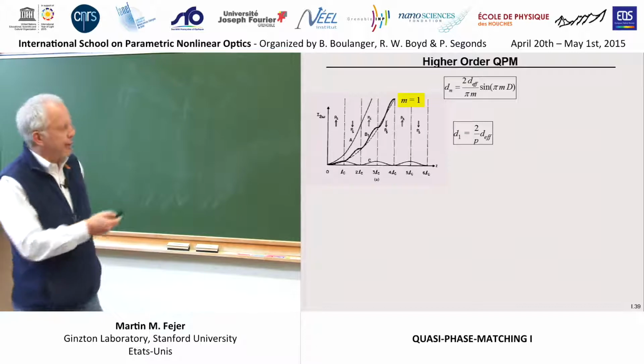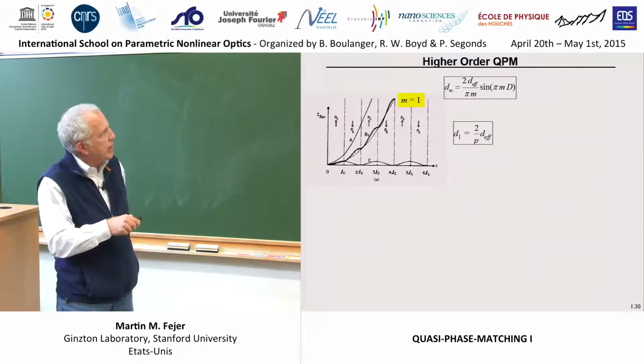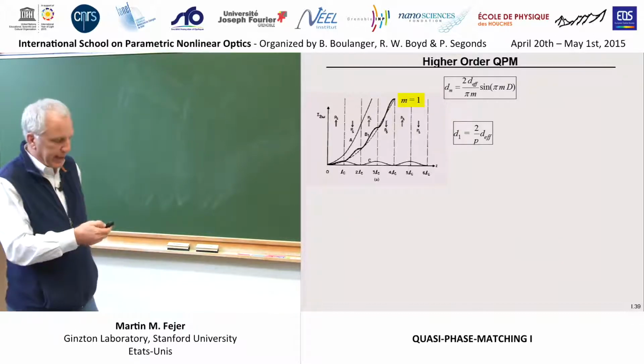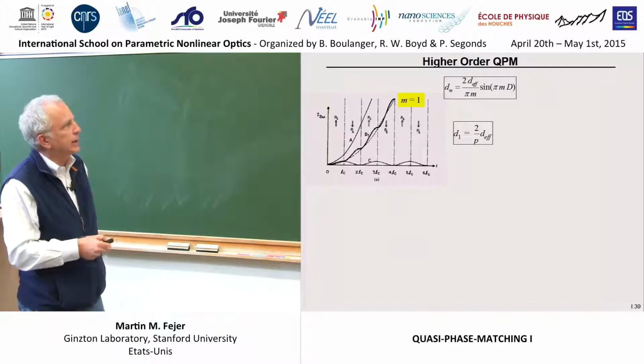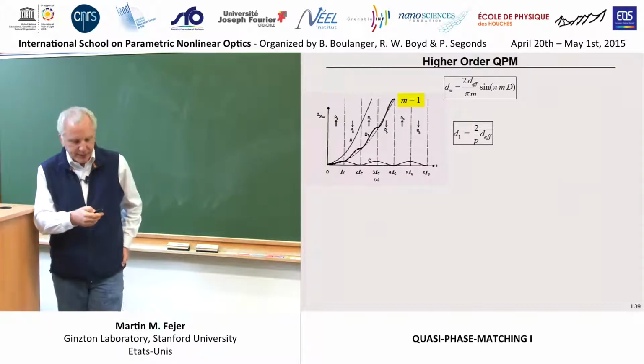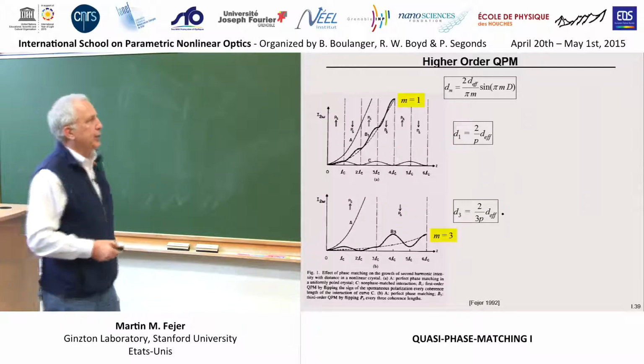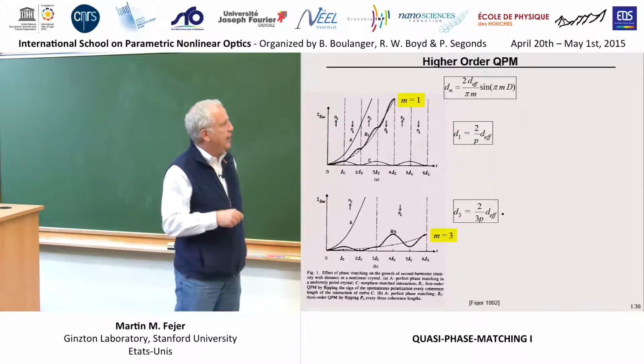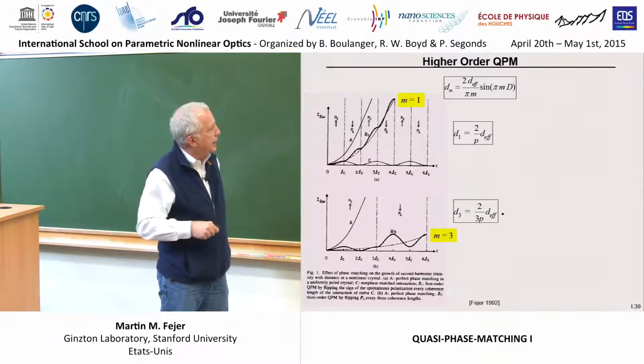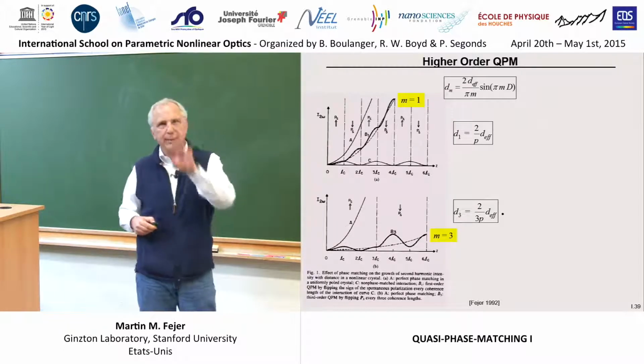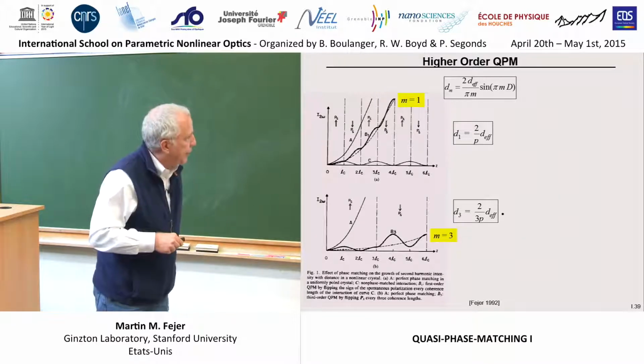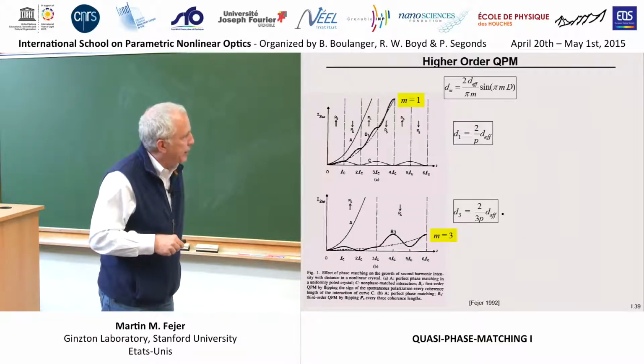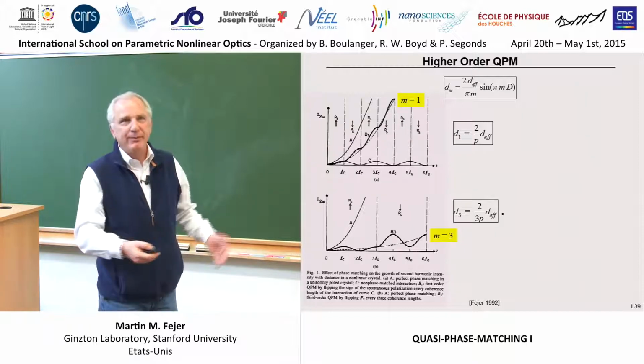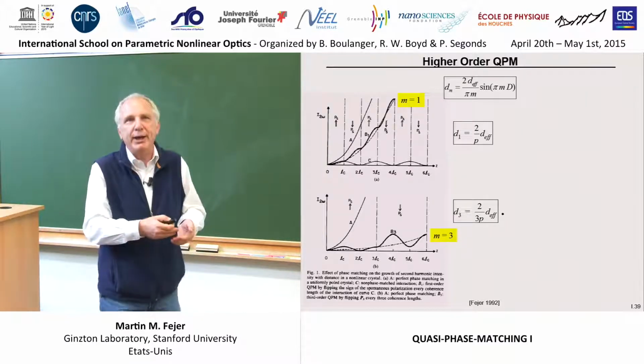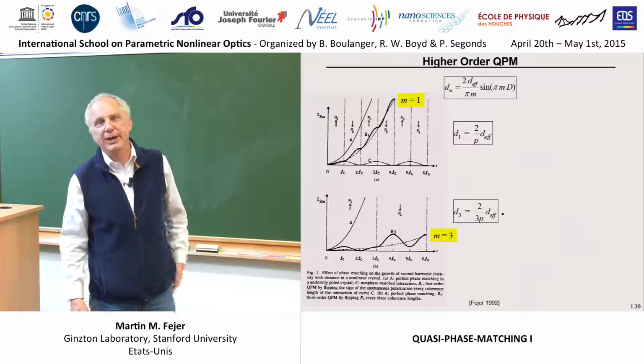Well, for the m equals 1 case, we've already seen what happens. Every time the waves get out of phase by pi, we flip the nonlinear coefficient, and we get this kind of growth. And that leads to d1, 2 over pi times d effective. Let's look at the m equals 3 case. So what happens? We said that now instead of being 1 coherence length long, a domain is 3 coherence lengths long. So after the first coherence length, you've generated some field. After the second coherence length, you've destroyed it all. And then on the third coherence length, you've created 1 coherence length's worth of second harmonic.